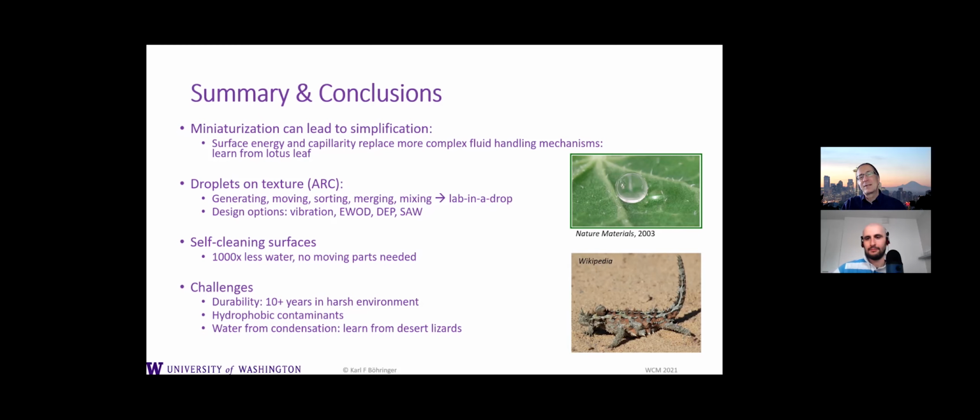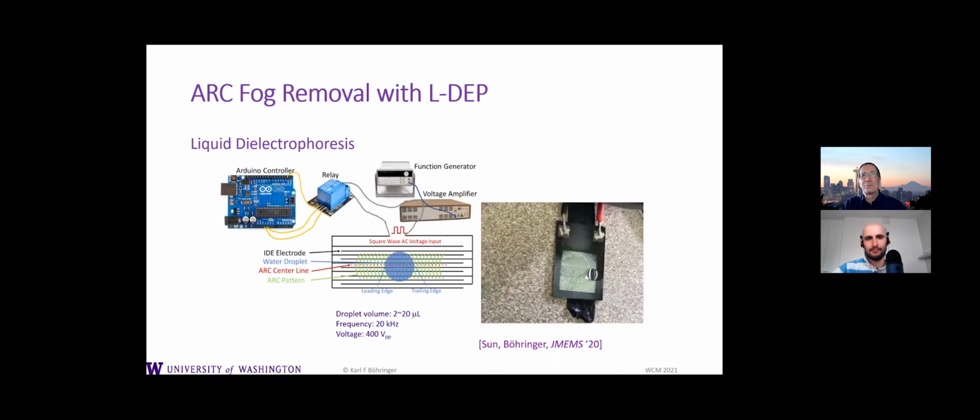So we presented some work, and I can show you one slide that I haven't shown you before that looks into cleaning surfaces, not in terms of dust, but rather in just moving condensation on that surface. The system that we tried out was a little bit different from what I've shown earlier, but the drops are, again, moving on these anisotropic patterns that are in this case transparent. We apply pulsed voltages that cause the drop to move sideways in this particular picture.